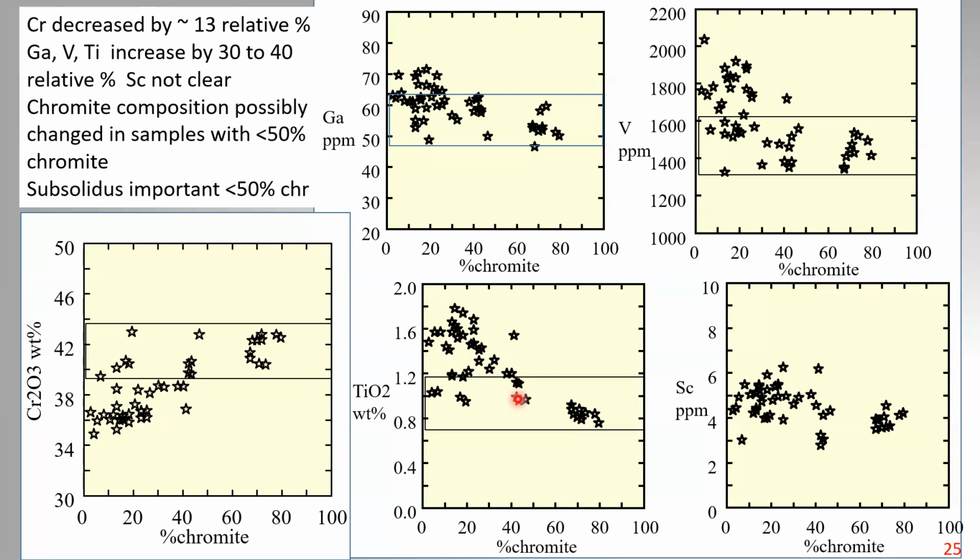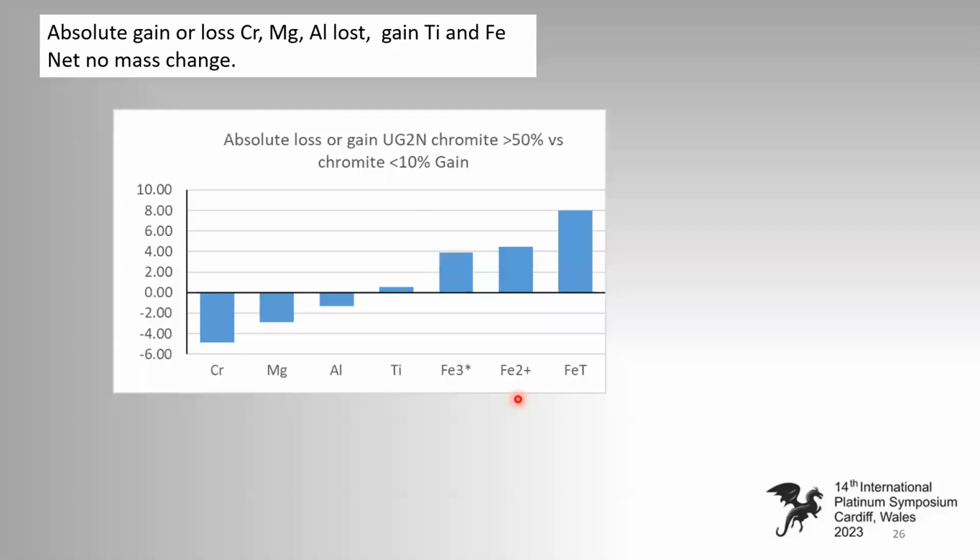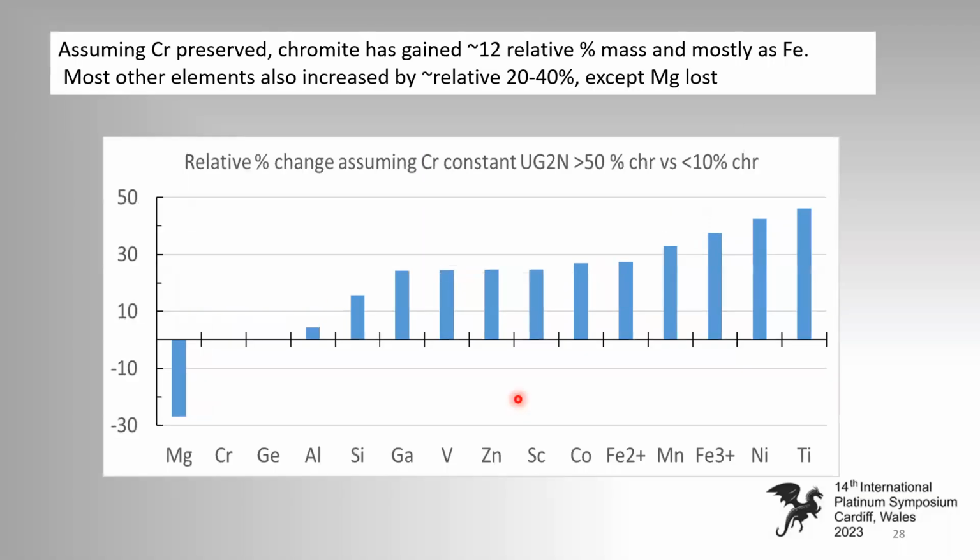Well, the difference is there's titanium in the other phases of the rock. Yeah, but if you look at the partition coefficient for chrome into chromite, it's like 100. The titanium, it's way less. So you don't have the same mass problem with any of the other components. It's only the chromium that's the problem. That's why I did that graph and said, okay, keep the chrome constant.